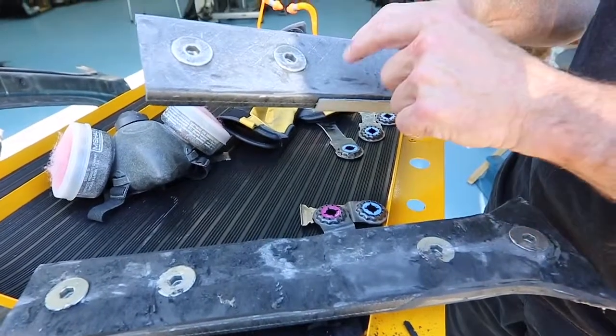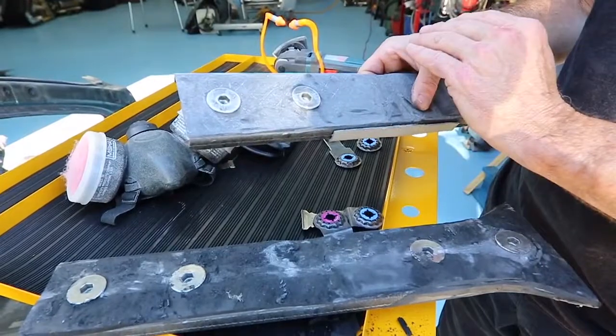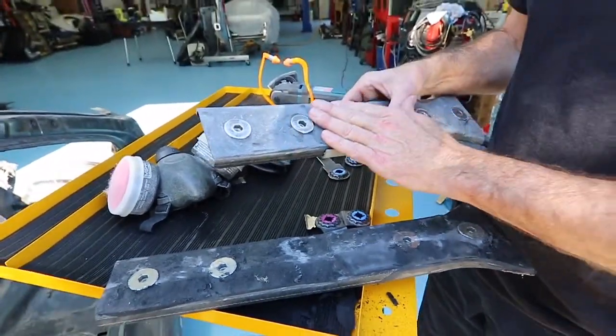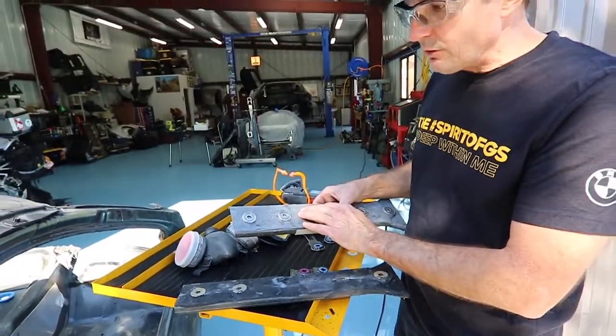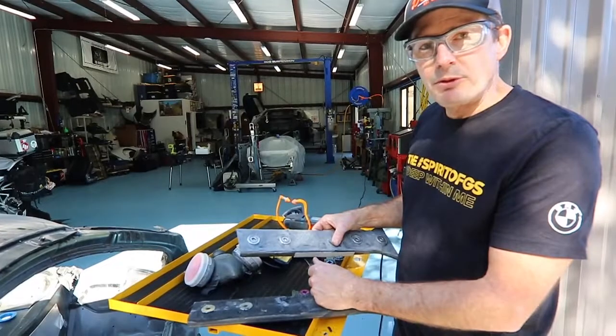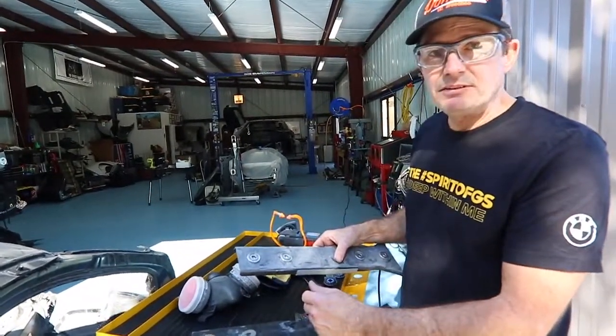The receiving surface gets the same treatment — it gets sectioned off, the bonding epoxy gets scraped off, a light sanding just to give a little scratch without cutting too much into the carbon fiber, and then an isopropyl alcohol wipe down. Then it gets bonded together with Permabond ET5429, a slow-cure two-part epoxy perfectly suited for this carbon fiber.